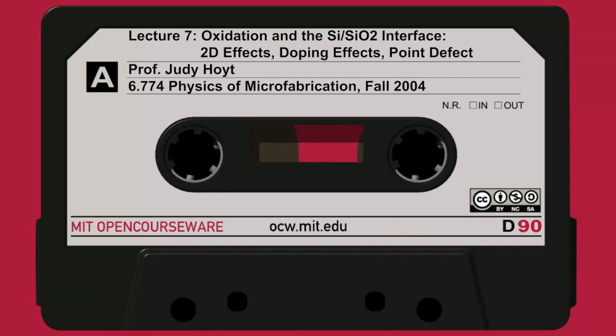This is a plot from his work, and the y-axis is the normalized oxide thickness. So this is normalized thickness to the thickness he grew on the flat surface of the wafer. So he measured the thickness on the flat part, and then he measured the thickness on these cylinder sides, and he just divided. On the flat part, he grew about 500 nanometers, or half a micron of oxide on all surfaces. And by the way, he's plotting this normalized thickness as a function of 1 over r, where r is the radius of the cylinder.